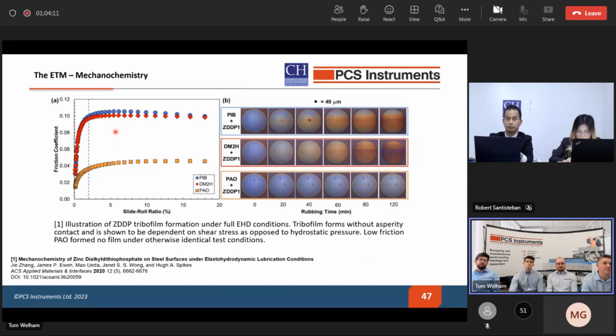And we see this shown here. These top 2 have much higher friction coefficients, and using the ETM slim, we see the development of tribofilms, whereas here, where the friction is significantly lower, under otherwise identical conditions, we see much less of a tribofilm.